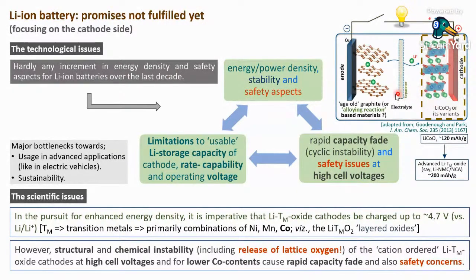Now let me put some numbers here. The anode side, which has graphitic carbon as the active material right from the beginning of the lithium ion chemistry, stores lithium ion up to a capacity equivalent to 372 milliampere hour per gram. So let's take it as 400 milliampere hour per gram, or a number 400 for the anode capacity. Now the cathode capacity to start with was between 120 to 140 milliampere hour per gram. So less than half the anode capacity.